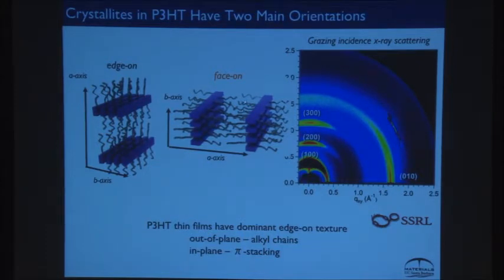We call this one edge-on. We call that one face-on, where the substrate is down here. If I look at the diffraction pattern, I would see spacing from the A-axis if I was face-on down here, and I do. I see that. And I see this distance, we call the pi stacking, the separation between chains here, and that's up here. The edge-on stuff is more ordered.